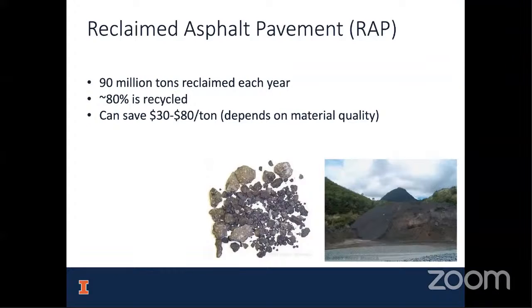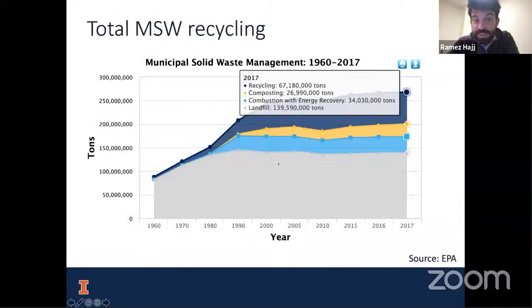And just to give you an idea how big this industry is in the United States, if you look at our total municipal solid waste, so this would be the things that people living in a city would use, for example, disposable plastics, disposable aluminum, those kinds of things, you will see that 67 million tons of those everyday products are recycled, which means that asphalt, as I mentioned here, 80% of 90 million is recycled. So actually more asphalt is recycled than all these municipal products combined. So just to give you an idea of the scale, asphalt recycling is probably the biggest recycling industry in the United States. And asphalt can actually become the world's most recycled material. So this is not a small niche industry. This is a huge, huge operation that involves everyone. And if you can use more and more RAP and have a good performance of your pavement, you can see how this can go extremely far in producing sustainable roads.